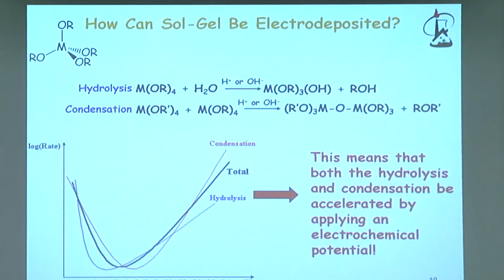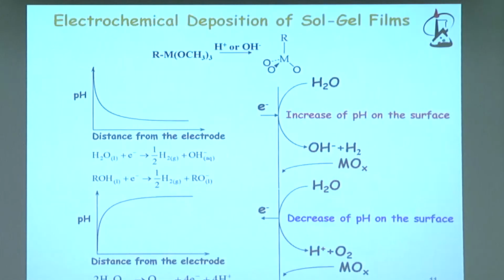You can do that by understanding that both of these processes, the hydrolysis as well as the condensation, are very sensitive to change of pH. And you can see here that the rate of hydrolysis and condensation accelerate both at acidic as well as basic conditions, which means that if we change the pH on the electrode surface, we can basically catalyze the sol-gel formation. And indeed, that's exactly what you can do. If you use protic solvents such as water or alcohol, and you, for example, reduce the solvent, you elevate the pH, you form a gradient of pH from the electrode surface to the solution, and vice versa. If you oxidize water or alcohol, you decrease the pH. Because of that, you catalyze and cause the deposition of the sol-gel.